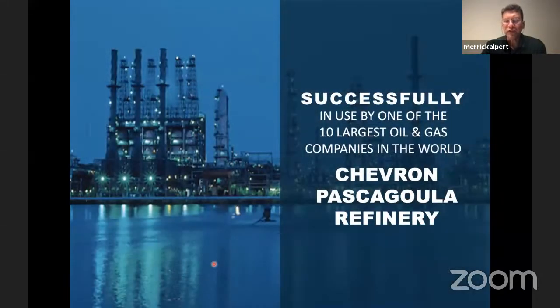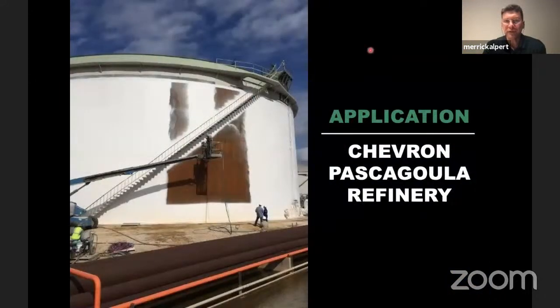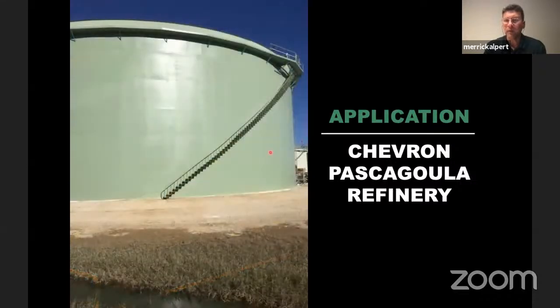Now, what I'll do is show you a couple of photographs as we're finishing up so you can see what it looks like in the real world. This is one of Chevron's tanks. The first thing that should jump out at you is, look at that level of rust on that tank. Look at that flash rust. With Eon Coat, we actually spray it on flash rusted steel, and there's no issue. Because of course, we'll use that flash rust, we'll use that Fe to help create the passivation layer. So notably, that rust on the tank is not our enemy, it's actually our friend, because it's going to help passivate the steel. And then, after it's been spray applied, a top coat goes over it.